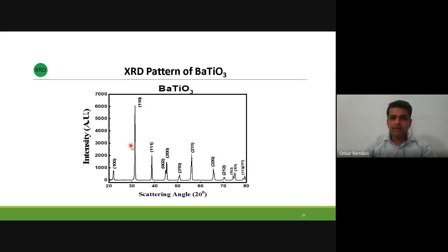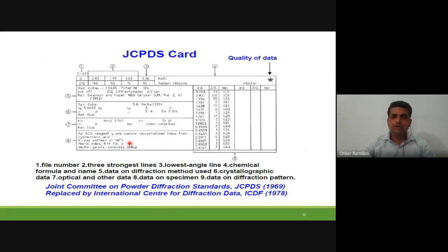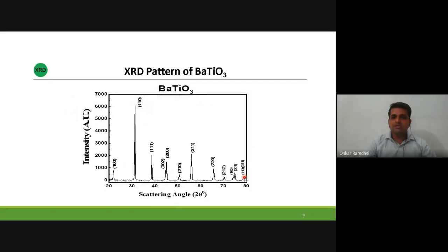Once you compare your data with the standard one, if it matches well, then what I can say is that the sample I have synthesized is in pure form. It has a tetragonal structure, and it has no impurity phases. If there is one additional peak, let's say at 35 degrees, then I can say the sample I synthesized is not in pure form. That may be due to oxidation of some materials. If you're using bismuth or any such material, we know that they are volatile. We are supposed to get the additional peak once you sinter the sample at higher temperature.